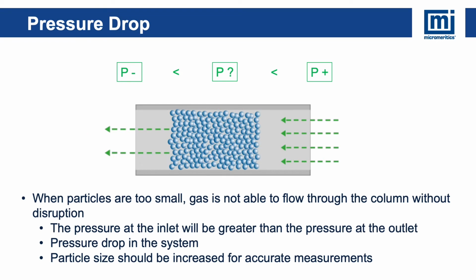Next up, let's talk a little bit more about pressure drop. As I said before, when particles are too small, gas is not able to flow through the column without disruption. As we can see here, as we decrease the size of our particles, the interstitial void between those particles gets smaller and smaller. As we increase our flow rate, that flow of gas is not able to completely flow through the void space provided by our particles. That will result in pressure drop, in which at the inlet of the column the pressure rises, and at the outlet of the column the pressure drops.